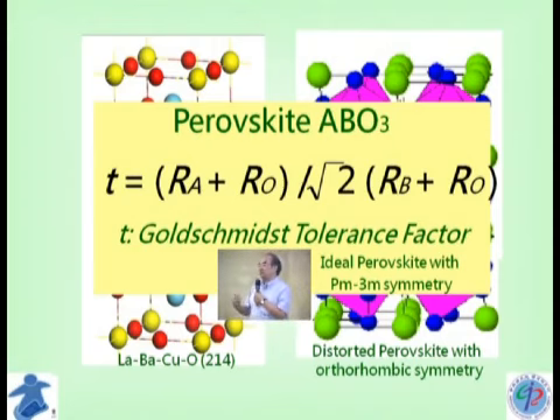This kind of perovskite material has been investigated for a long time, and a long time ago an important guideline was established, called the Goldschmidt tolerance factor, right? To keep this perovskite structure properly, the size of the elements or ions involved has to fit some kind of criterion. This tolerance factor cannot be too small or too large; there's some range you have to be in. For the ideal case, this t will be equal to 1, for ideal perovskite. But if it's distorted, it could be 0.96 or something like that.